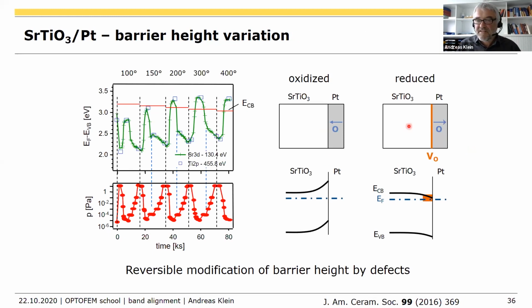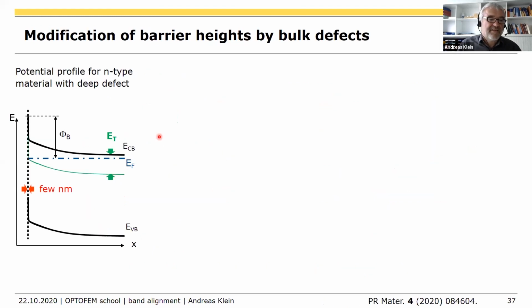I'm pretty confident that these defects are really directly at the interface. But there's also something else: if you have defects in the bulk of your material, let's consider a defect which is, let's say, a trap level, some distance from the conduction band minimum in an N-type semiconductor. Now you want to raise your Fermi level. No, you want to lower your Fermi level, so you want to have a lot of upward band bending.